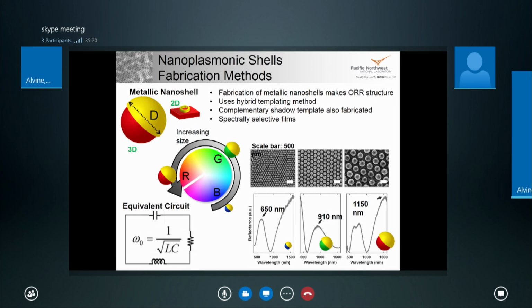The nanoshell is actually the open ring resonator analogous structure for microwave metamaterials. So this is the 3D nanoshell, and this is the 2D open ring resonator structure you'd see in microwave metamaterials. As you increase the size of the structure, as I showed before, you get a change in the resonance, so you can tailor that anywhere from the UV all the way to the near infrared. Typically, because we're interested in window films, we've been looking at near infrared responses, so we're looking at structures on the order of 100 to 300 nanometers in diameter.